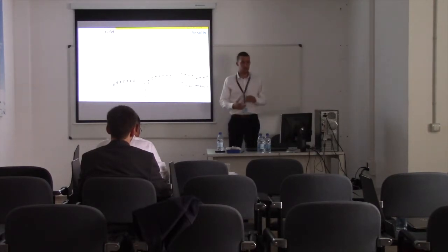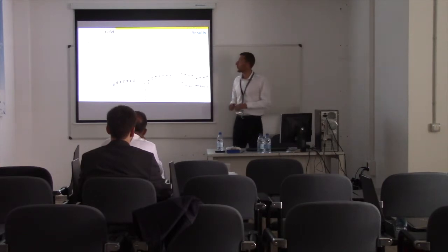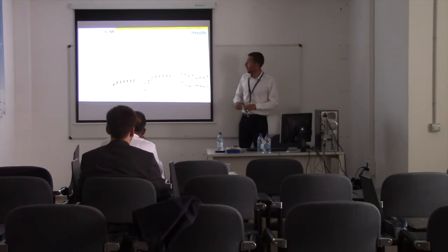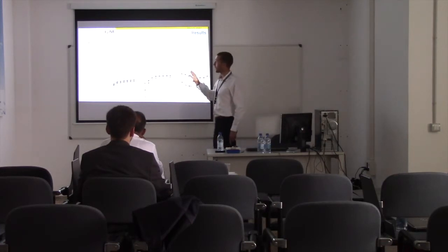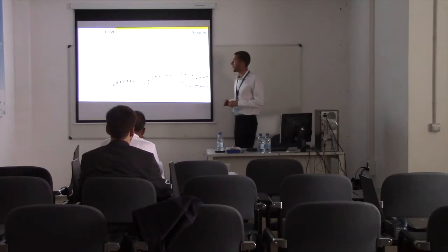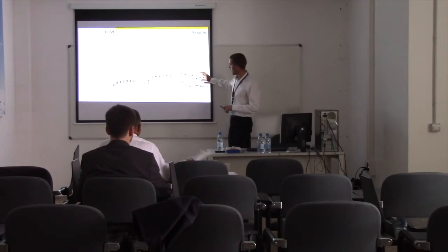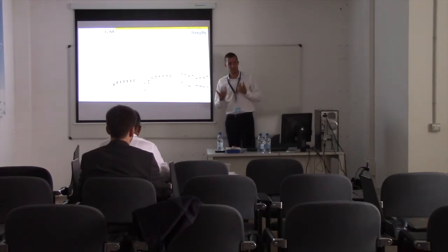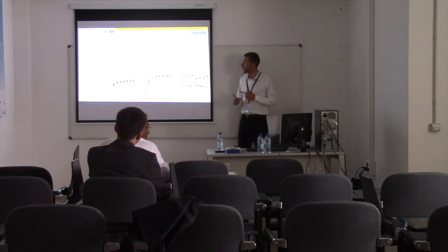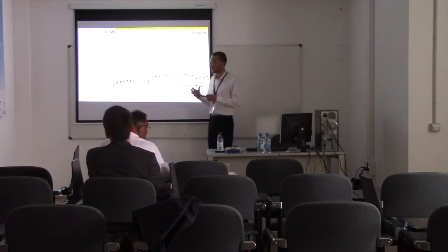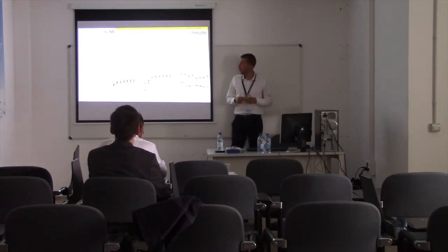So now I will present you a few results. For the fixed velocity at 50 millimeters per second, we had two kinds of results depending on the recoater system. First, for the blade, we observed a flatter powder bed layer, but the roller seems to have a more significant impact on the packing density and the coordination number. Roller can introduce more force and can let more arrangement in the powder bed layer.